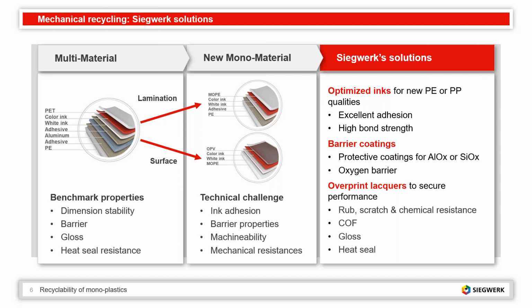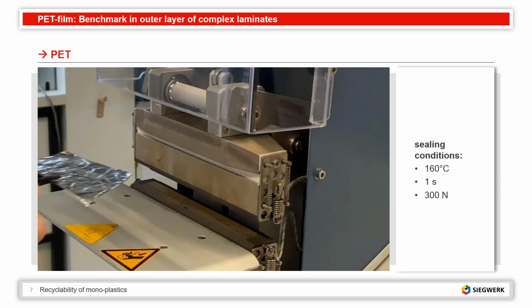And there is one nice example that I'd like to show you here because it's also easy to show. That's the heat sealability. And I will demonstrate what Siegwerk can do for you here with a few clips. What you will see here in a second is we have put a film between two aluminum layers, and then we put this aluminum film sandwich in our little sealing device here. It's a lab device, and the aluminum is only there to protect this little sealing device because our co-worker didn't want to clean the device after each trial. And here, as a benchmark, we put in PET.